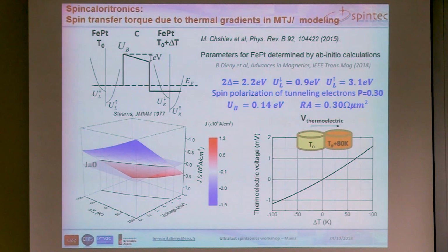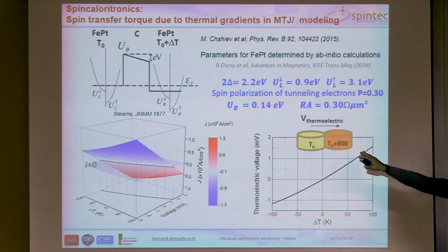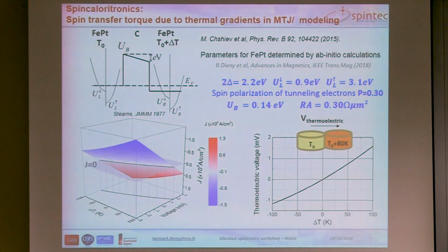So by using Schrödinger equations and formalism described in the paper here, we can basically calculate the current flowing through the tunnel barrier as a function of voltage and difference of temperature between the two electrodes here. And so we obtain a two-dimensional surface here. And of course, in the media, there is no charge current flowing between the grains, because what happens is that there is a thermoelectric voltage which appears between the grain, which compensates the fact that one grain wants to emit more electrons than the others. So by setting the current to 0, we can determine the relationship between the thermoelectric voltage here and the difference of temperature between the neighboring grains. So for instance, 80 Kelvin would give something like 1 millivolt between the neighboring grains.